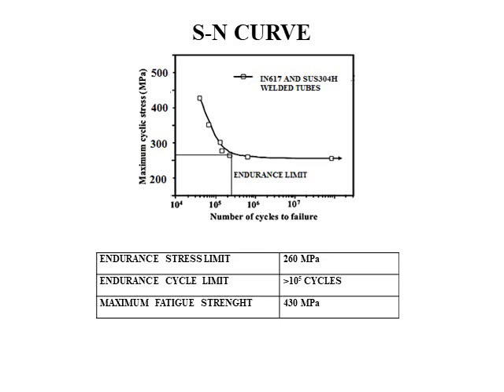It is showing that the endurance limit is at 260 megapascal. Hence there is an inference that the endurance limit of 260 megapascal is maintained, which means the tube will have a maximum lifetime of more than 10 power 7 cycles, that is, more than 10 million cycles. The maximum strength of the material created is 430 megapascal, and the endurance limit is greater than 10 power 5 cycles.